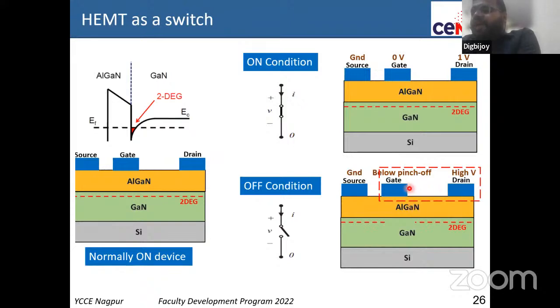So as you keep applying more and more reverse bias, you're basically depleting the 2D electron gas towards the drain, and eventually the limit of the spacing will decide how much voltage you can block. Now you can say that I can increase the spacing between gate and drain so that I can block more voltage. Yeah, sure. But then if you increase the gate-drain spacing, your on-resistance will increase, which means your on current will decrease, because if you make a resistor longer, it becomes more resistive, right? So that's why it's a trade-off. It's a sacrifice between the breakdown voltage and the on current also.